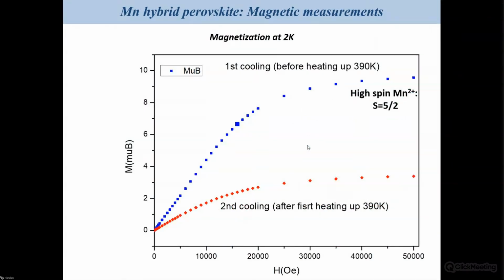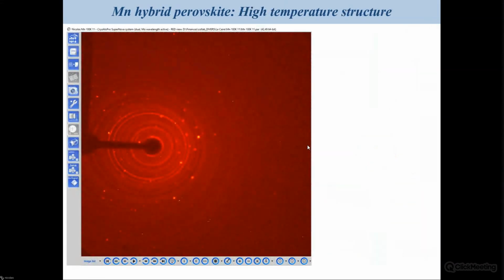If you want to model the magnetization obtained at 2 Kelvin, it's very easy to model it with two interacting manganese 2 plus atoms with a spin 5/2, but it's not possible to explain what happens after the first heating because the signal is completely different, as you can see on the red curve there. So we tried to obtain the structure after the first heating, and this is the result of the attempt we made. You have a huge contribution from powder diffraction and a small contribution from the surviving single crystal in your sample. So it's very difficult to deal with that.